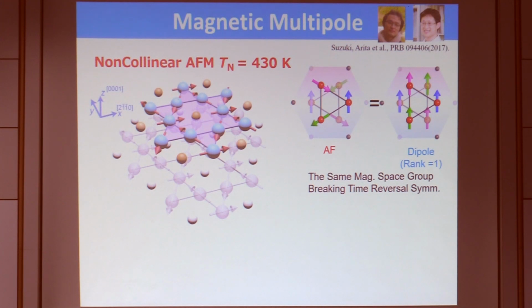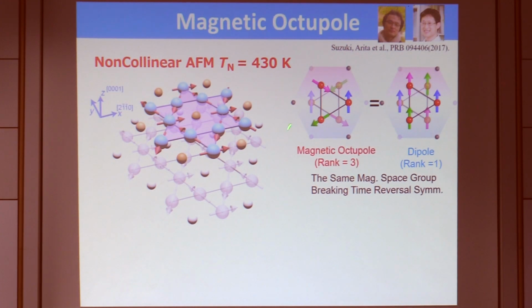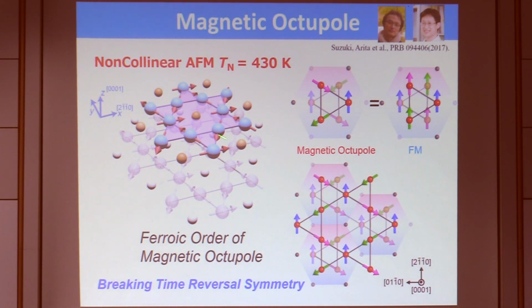is not allowed, and the minimum rank allowed is 3, which is a magnetic octupole, and this actually breaks time reversal symmetry. So one can view this magnetic texture as a ferroic order of this cluster, namely a magnetic octupole. So it's basically a unit that breaks time reversal symmetry macroscopically. That also allows us to observe a dynamic version of the anomalous Hall effect, which is the Kerr effect and also Faraday effect. We have also seen the Faraday effect recently by using thin film, but time is so limited,